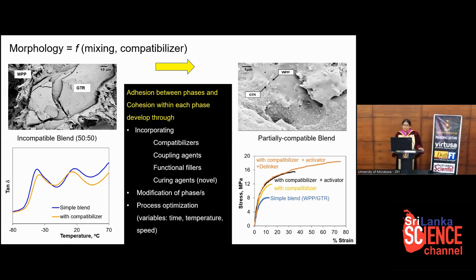The incorporations can be either a compatibilizer or a coupling agent, a functional filler, or a novel curing agent that is not commonly used in the rubber industry. Since the blend is microscopically heterogeneous, the tan delta curve in the thermal characteristics shows two peaks for the two glass transitions of the two materials. But if we use a compatibilizer or add cohesion inside the blend, the two glass transition temperatures become closer and show a somewhat homogeneous nature. If it becomes a single peak, that means it is perfectly homogeneous, and that cannot be expected from polymer blends at all.